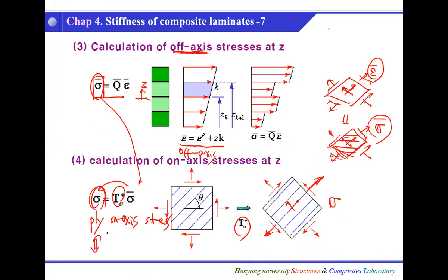then, which we're going to define, okay? We didn't define yet, but we have all kinds of strengths. We don't know yet, but don't worry, we will study that. It's like when you have stresses in isotropic material, what do you need to do? Well, you have a yield strength, and then you calculate the von Mises stresses, right? You compare these, and whether it is smaller, larger or equal, that's how we design. If you want to introduce some safety factor, then this is 10, and this should be 20. So that's the way we introduce a safety factor. The concept is very similar, but the difficulty comes from the fact that we have five different strengths, not just one. That makes a big difference. So rather than von Mises theory, we do need a certain type of failure theory. What is that?